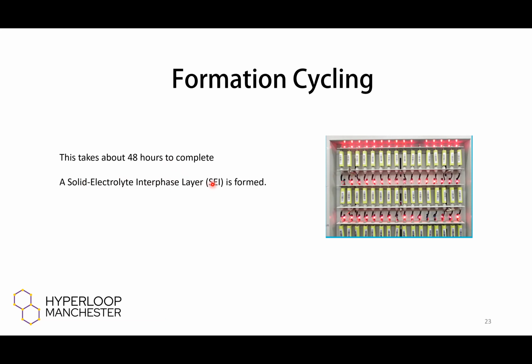But the main reason you're doing this is to form this solid electrolyte interface. This is a layer that's formed on the materials inside of the battery, and essentially it's like preferential corrosion. So you're pre-corroding the materials in a way that stops them being degraded in a more detrimental way to the longevity of the cell, and you do it under certain conditions. And this is really driven by adding certain additives into the electrolyte, so additional salts or solvents that go inside of the system, and these form a preferred SEI layer, and that helps keep the battery cycling for a long time, unless it gets broken, which can happen for certain reasons.